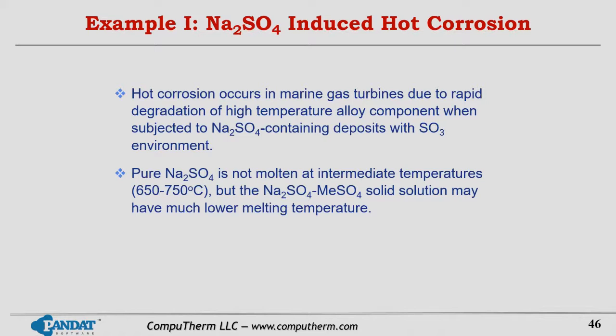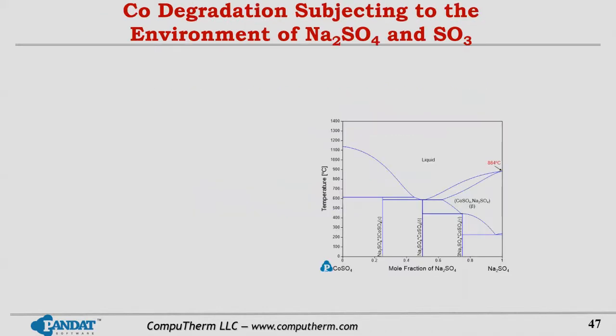We know that sodium sulfate does not melt at intermediate temperatures, such as 650 to 750, which is mostly the application temperature. But when sodium sulfate forms a solid solution with other metal sulfates, the melting temperature can decrease quickly.